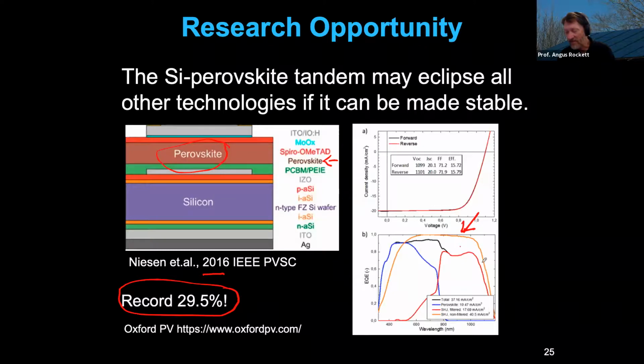But the net result of the two devices is this orange curve, which shows that you're collecting all the way across the solar spectrum, from way out at the long wavelength band to way down at the short wavelength band. And so each of the two individual cells produces, we design those two energy gaps so they produce the same amount of current, and we add the voltages because the devices are in series, the voltages add at constant current.